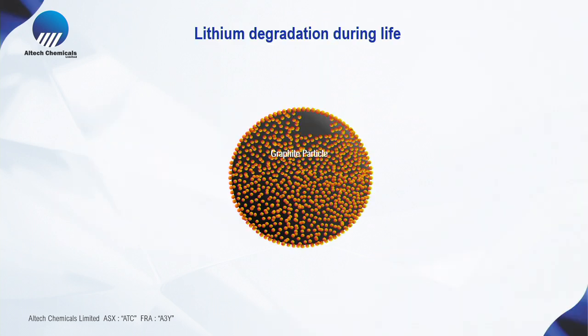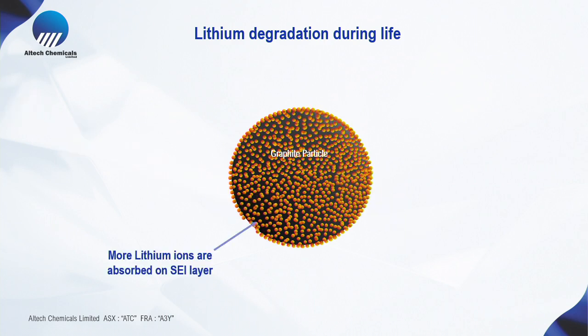One of the other things in the life of the battery is that the electrolyte is a lithium hexafluorophosphate. And during the performance of the battery, any moisture in the electrolyte forms hydrofluoric ions, and it breaks down the SEI layer. And as it breaks down the SEI layer, more lithium is absorbed, and so you see a degradation of lithium through the life of the battery.